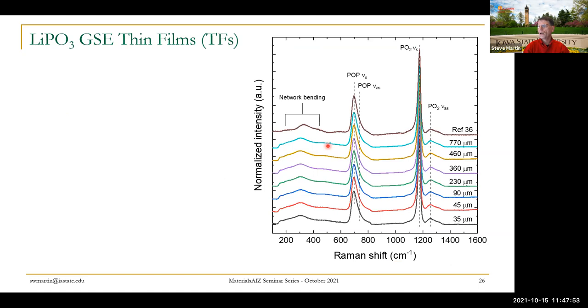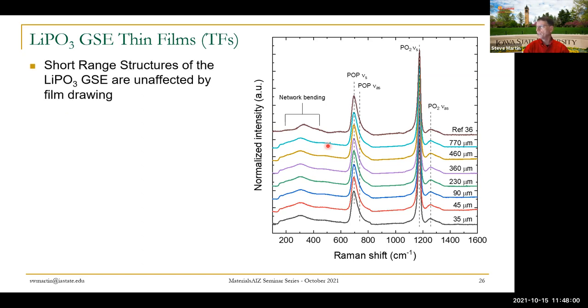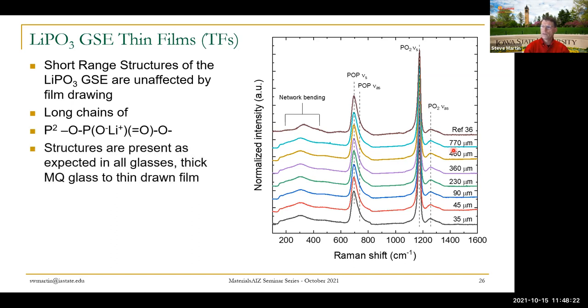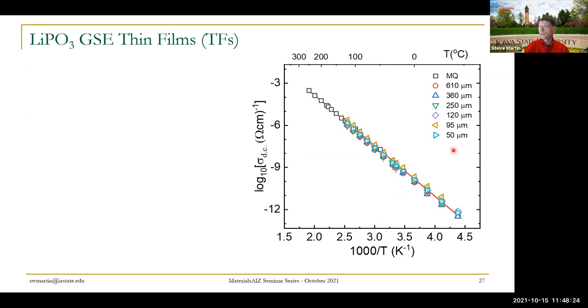Let me finish up then, just to show you a little bit more data on LiPO3. The films are identical to the bulk, and you can see we have the bulk, which is reference 36. We have a variety of different films from 35 microns all the way to about 700 microns. It's hard to do NMR because they're so thin, but Raman spectra can be done, and they have beautiful reproducibility. There's just the long chain of these PO2 groups, and so the structures are present as expected.